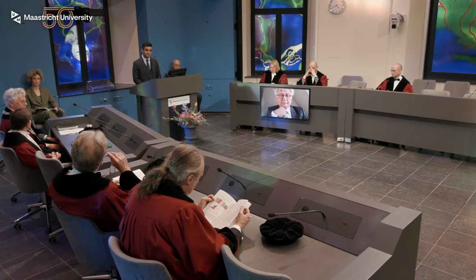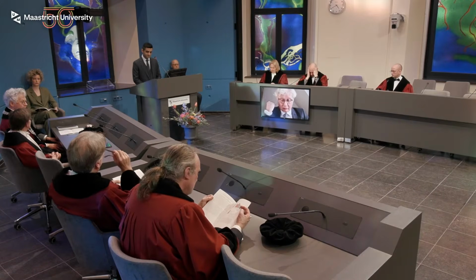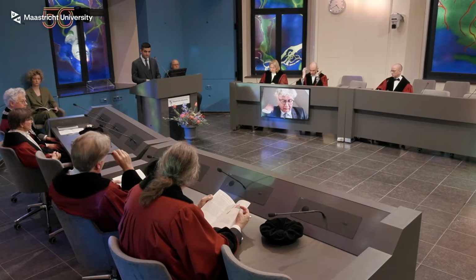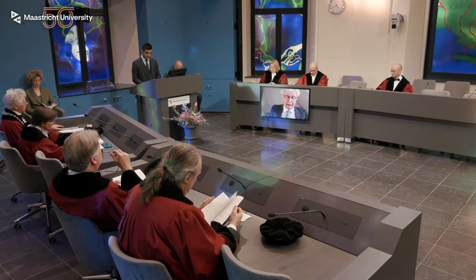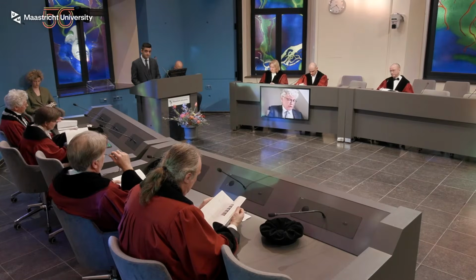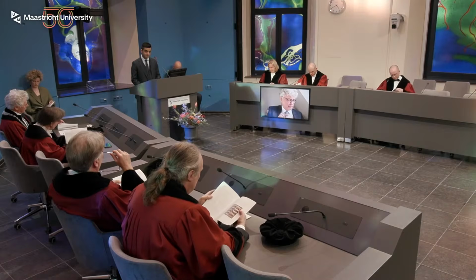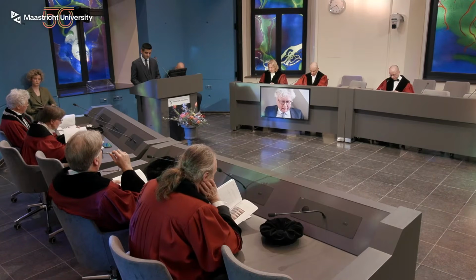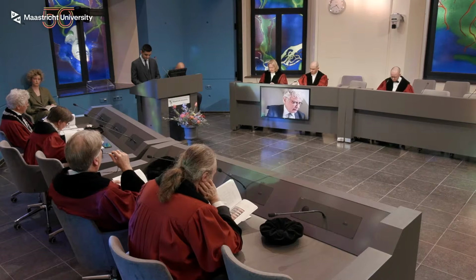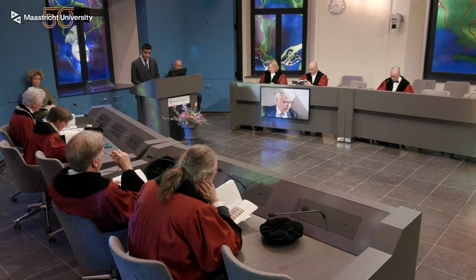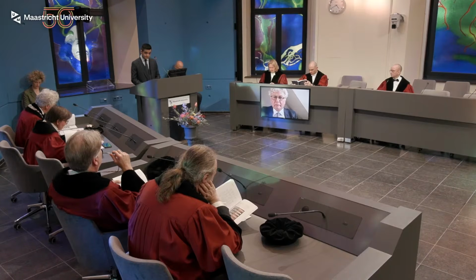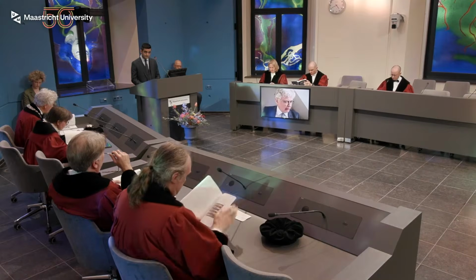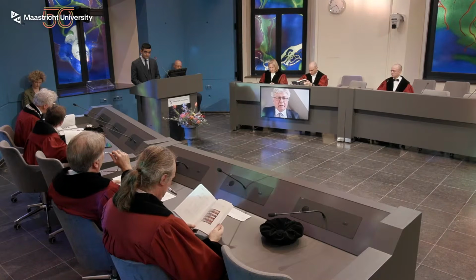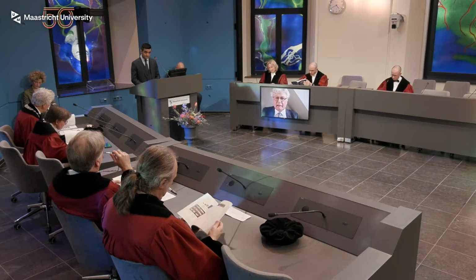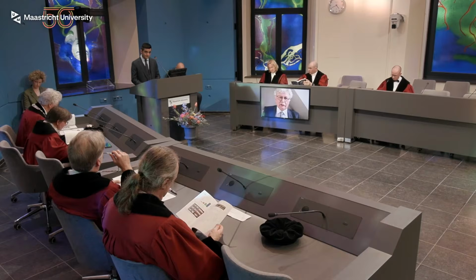Now, to ensure that the fracture is brittle, you added some pictures in the appendix at figure S2, page 151. And when I look at that, the first thing that comes to mind when I look at these pictures is that the fracture surfaces look symmetric. So it's like there is a horizontal line and it's kind of mirrored. So I don't recognize the pre-notch in these samples. Could you indicate where they are? How is it always on one side?